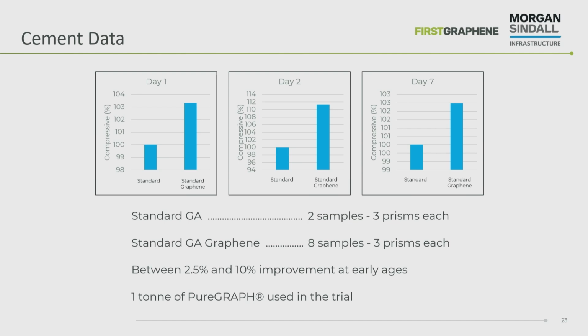We did some trials, so we took about 20 different samples out. Obviously this was running for about 8 hours. We used a ton of graphene in that trial. That was powdered graphene, so it's very low density, so that's why it looks like so much in those pallets. Those 7 or 8 pallets there, but it only had about a ton of graphene in it because it's very low density. So we got this data here.